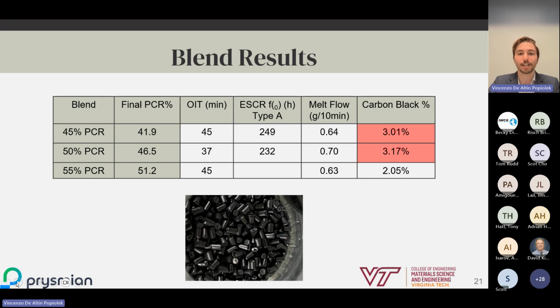For OIT, which had an industry standard of 20 minutes, we see that we were able to almost double industry standard for all of our blends. And again, if we wanted to increase this further, we could simply add slightly more antioxidants.